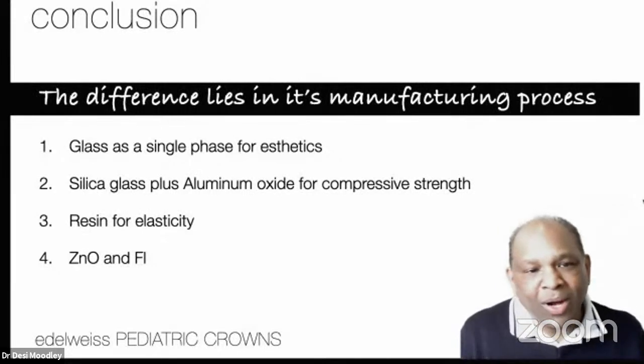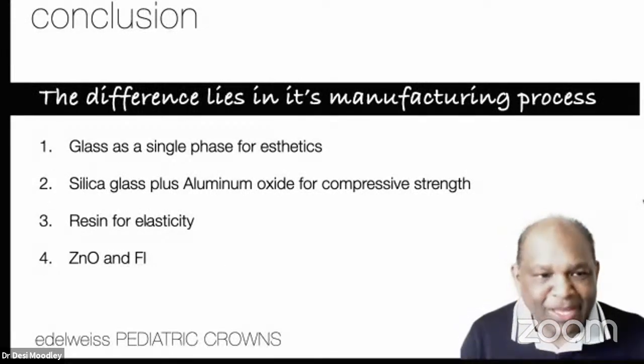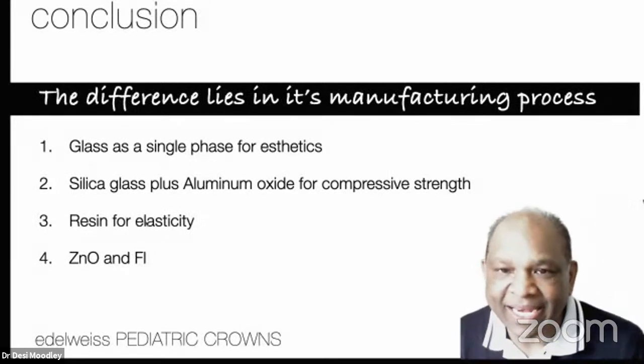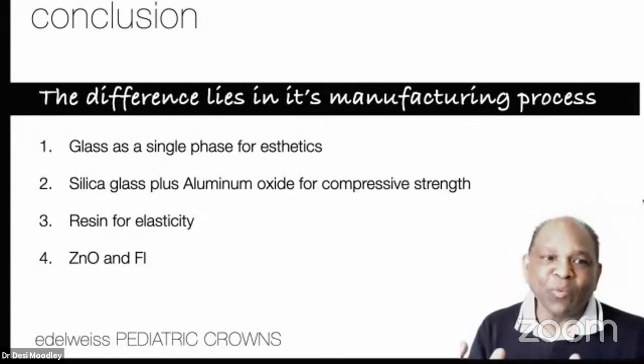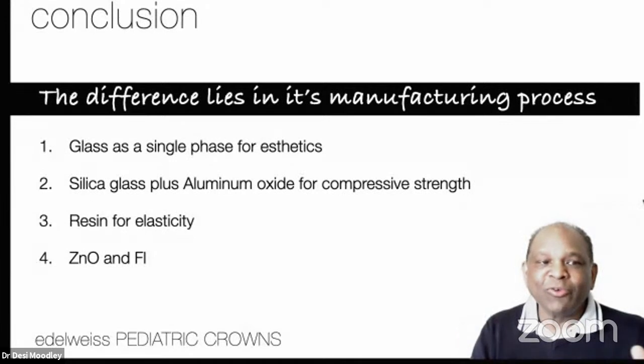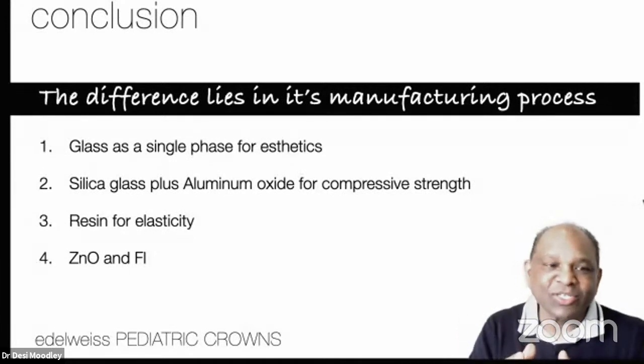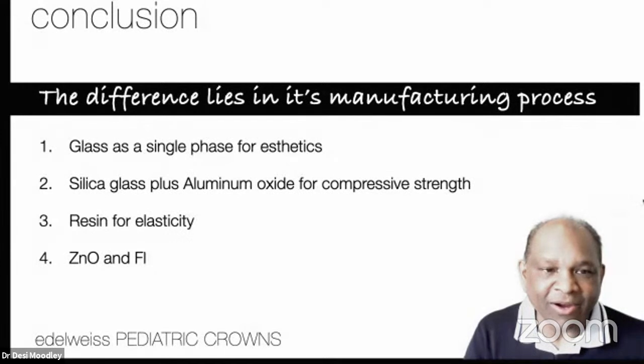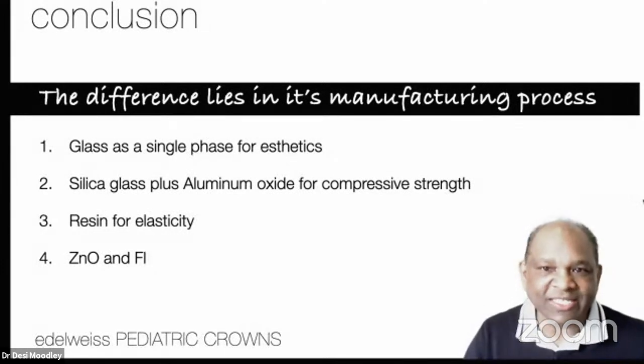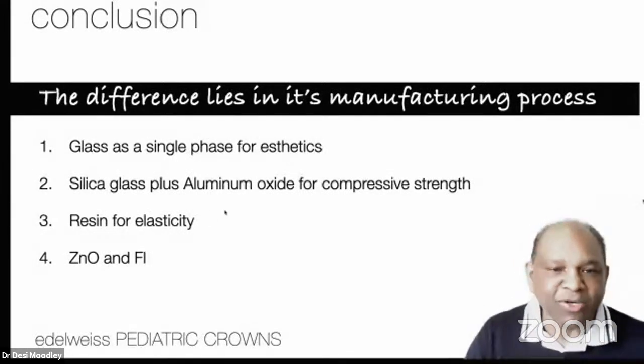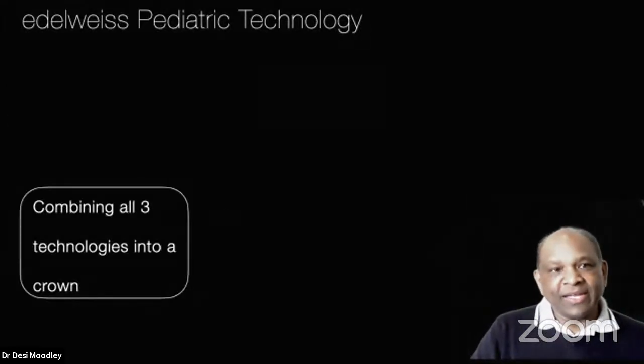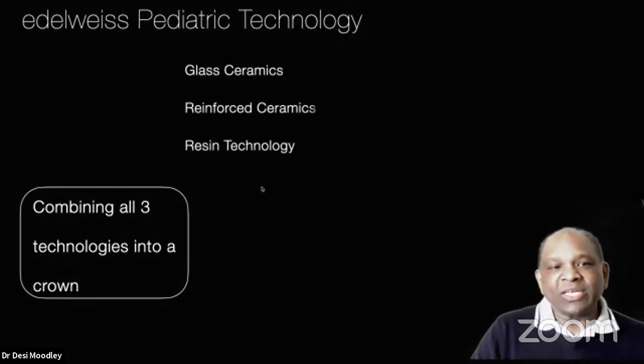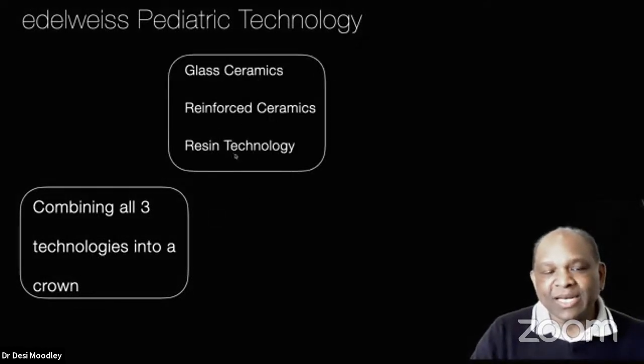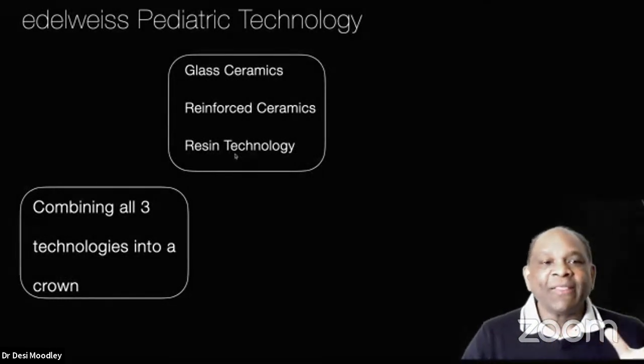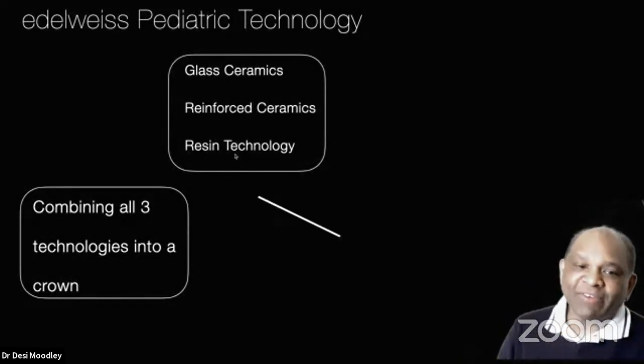So how is this possible? It mainly became possible because of the laser sintering and vitrification process, where they've fused the individual glass particles into one single mass of glass, and that's how you got the aesthetics. Okay, and by adding aluminum oxide, you could get the compressive strength. So in terms of the technology itself, it is combining all three technologies, the glass ceramics, the reinforced ceramics, and the resin technology into one single Edelweiss pediatric crown.